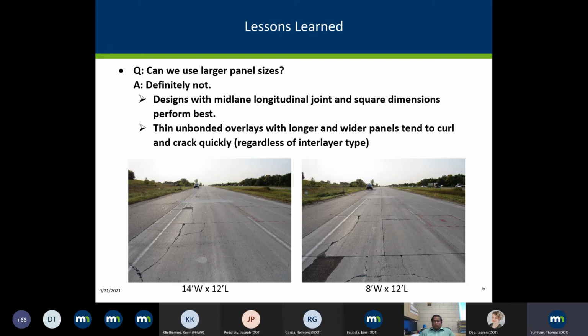Now, what's interesting is next to these two fiber reinforced cells is a set of cells that we constructed several years ago that just had 6x6 panels, no fibers, but sitting on the same concrete overlay on a fabric, and they're actually performing quite well. So again, this tells us that the fibers are not going to save us, and they're not going to allow us to increase our panel size beyond the typical 6x6. For something this, again, you're talking about a 5-inch pavement overlay.